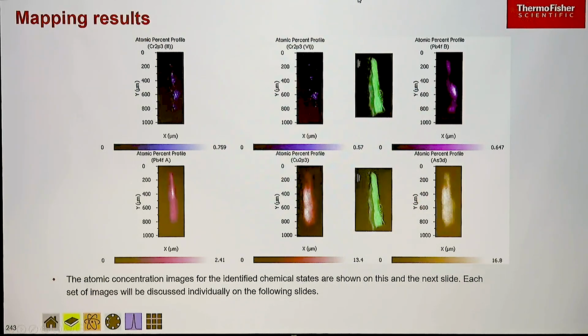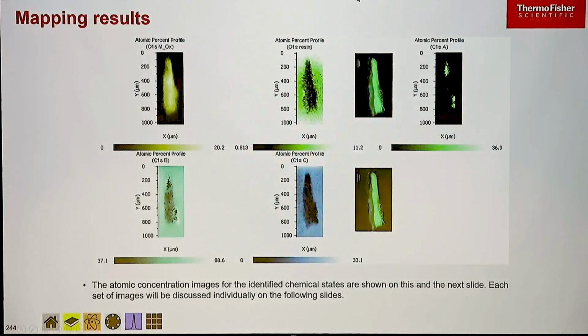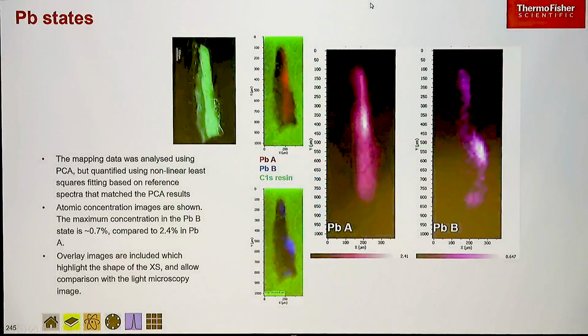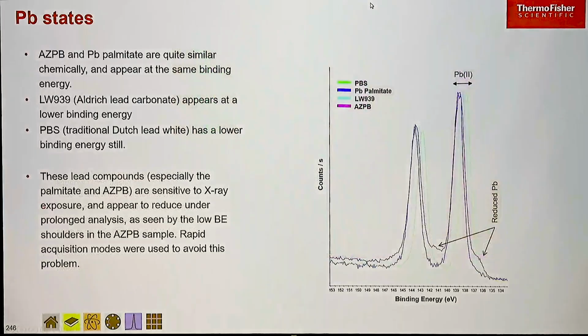We can see, again, principally in the green paint, metal oxides all over the place, and then a couple of different carbon chemical states as well, which aren't really important, but are probably some carbide or something that's forming in the sample. So it's the lead really that's of most interest. So we've isolated out the chemical states here. We've got this lead A where those little crystallites are, lead B around where that blister feature is. So let's pull out the spectra for those and compare them with some reference spectra.